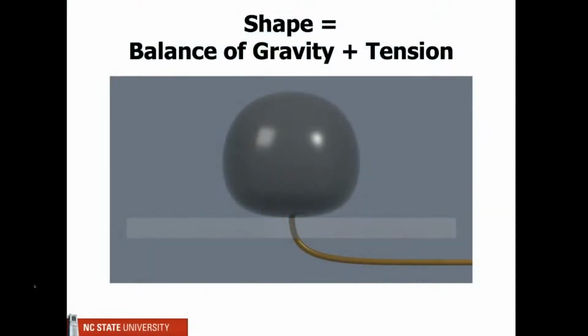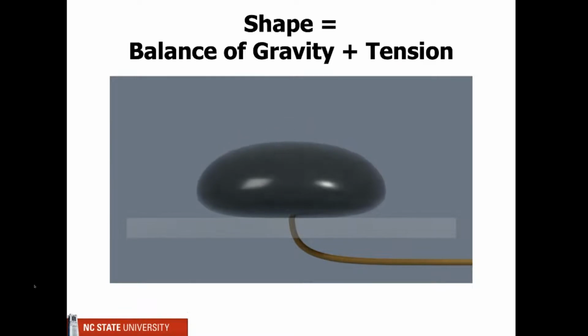So the way you can tell this is that the shape of a droplet represents a balance of gravity. So gravity wants something to be flat, right? And surface tension, which wants it to be a sphere. So in these experiments, we put a little electrode underneath it, and when you apply the voltage, when the surface tension gets lower, it will start spreading. Now, at very special conditions, we find something that's absolutely amazing, and that is it behaves as if the surface tension was 0. If the surface tension of a liquid is 0, it should just keep spreading and spreading and spreading.